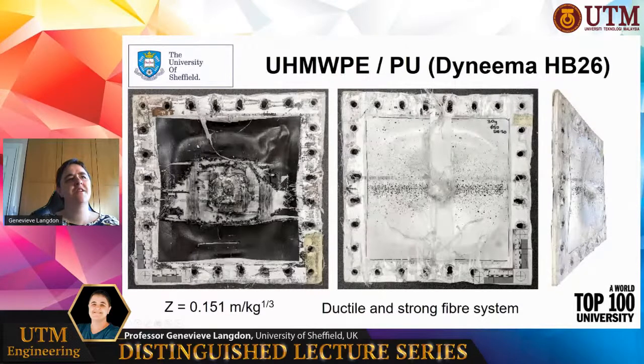You get some of that reverse displacement I was talking about earlier if you look at the side-on view on the right-hand side. So you get some snap-through buckling. You see a large permanent deflection of the panel. There's a small perforated region in the center, which virtually closes over when you rebound. There's tensile stretching, necking, fibrillation, broken fibers. There's an awful lot going on that makes this a very complex failure mode to understand, but it is a very promising material for the future.